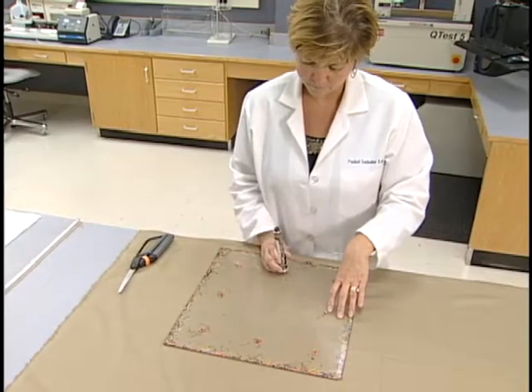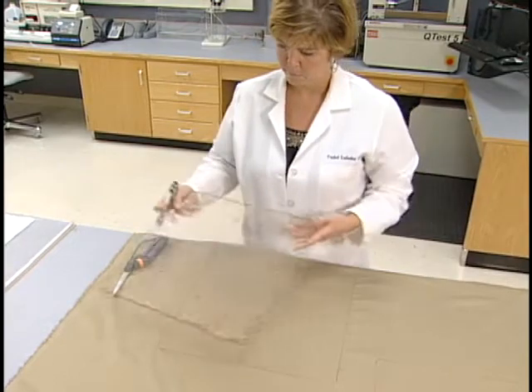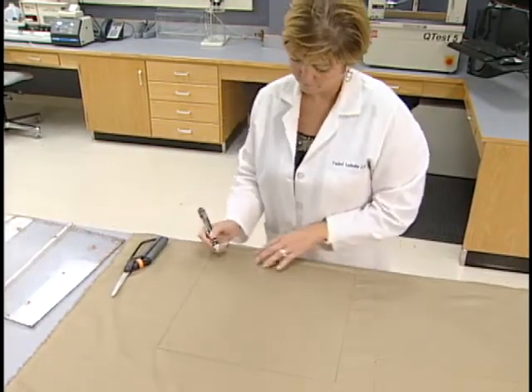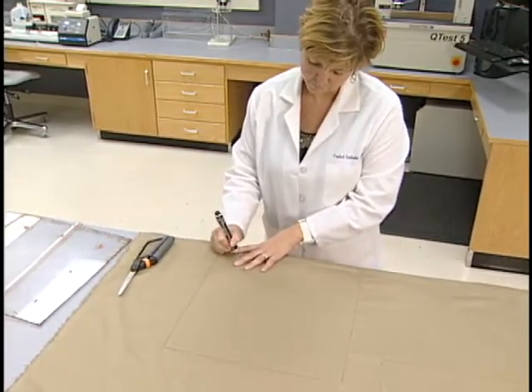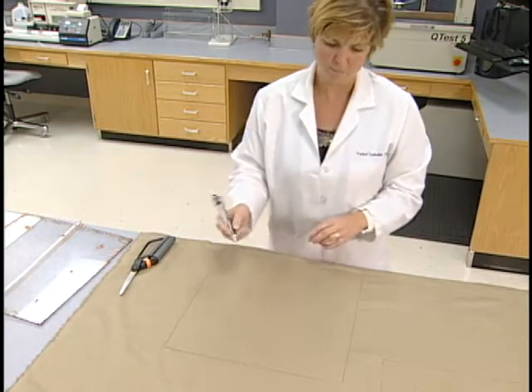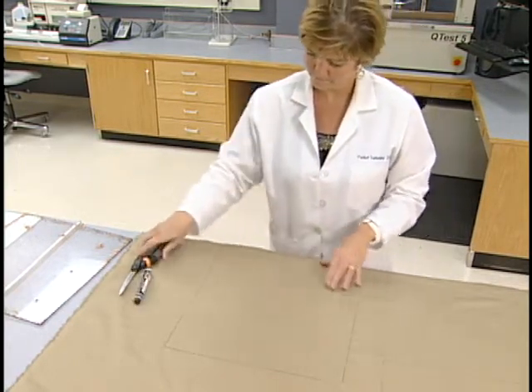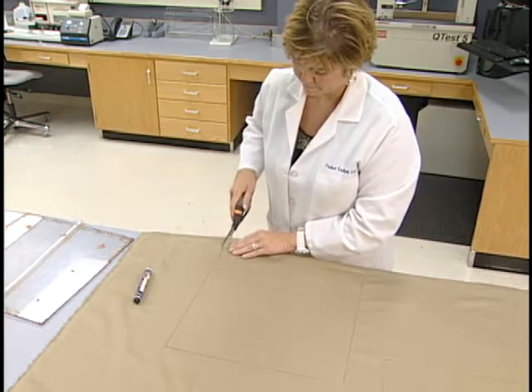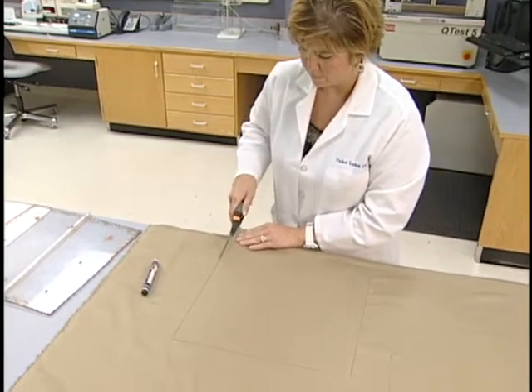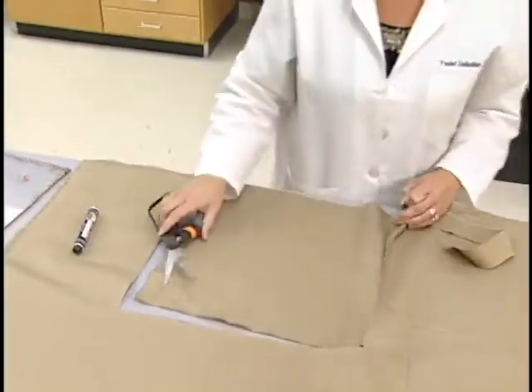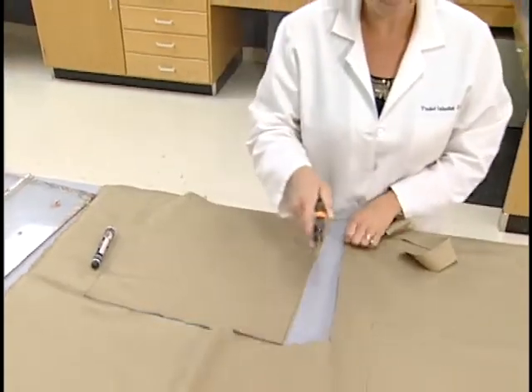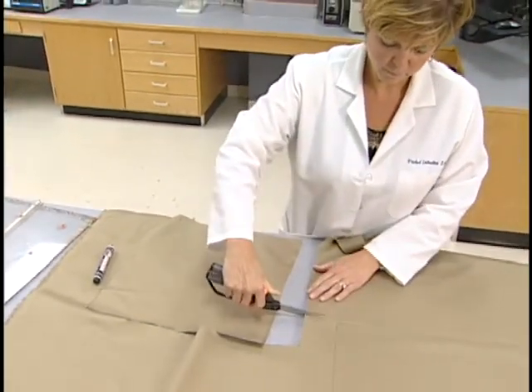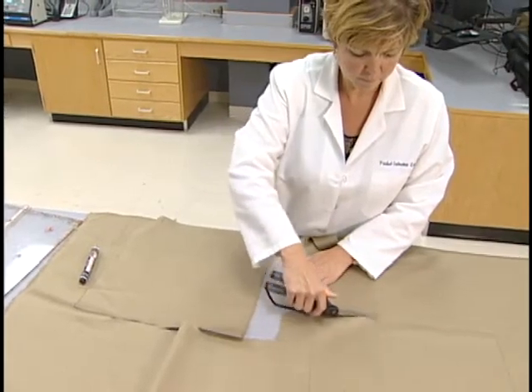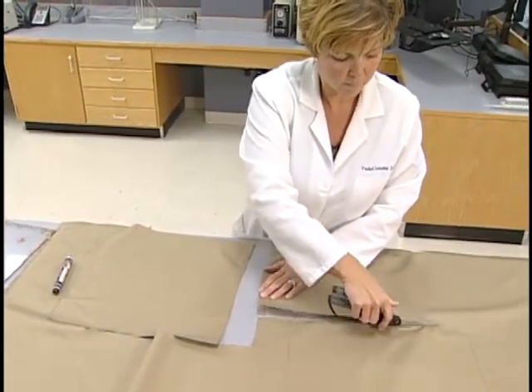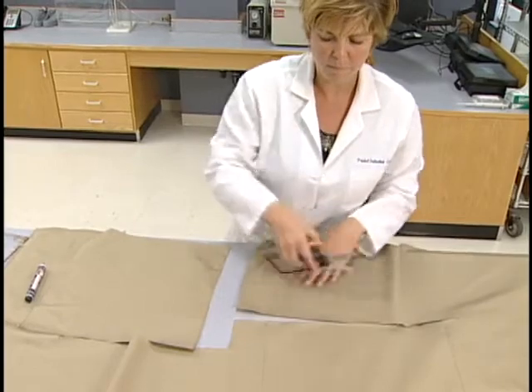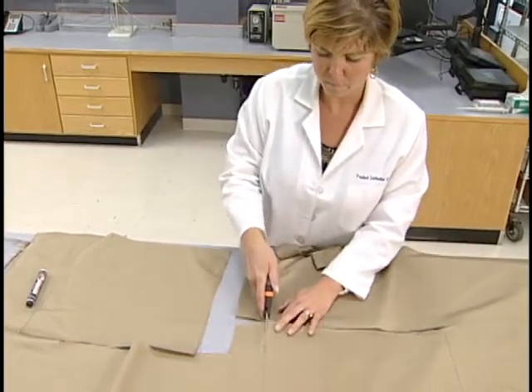In addition to the standardized equipment and detergents, the test method requires standard-sized samples and ballast fabric. 3 representative fabric specimens of about 15 by 15 inches, 38 by 38 centimeters, are cut parallel to the fabric length and width. Where possible, each specimen should contain different groups of lengthwise and widthwise yarns. The specimens should be marked to indicate the lengthwise direction. If fraying is expected in laundering, the edges of the specimen should be hemmed with a specified sewing stitch.